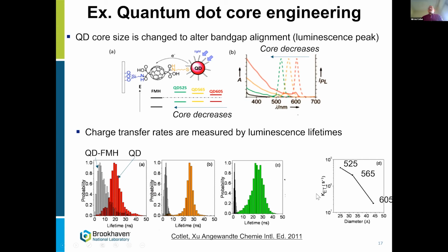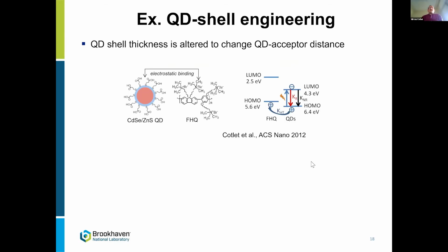So, calculating the rate for electron transfer, we see that by decreasing the size of the quantum dot, we actually increase the rate for electron transfer in a very controllable way. We can do quantum dot shell engineering, basically.